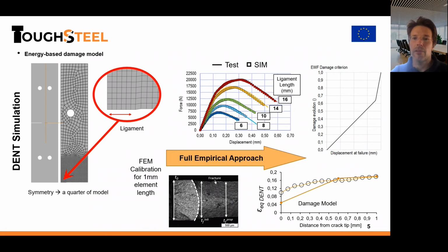To obtain the model parameters, we use a reverse engineering process where we simulate the DENT test and, through an optimization process, we change the model values until we obtain a good fit between the simulation and the results. The simulation model is a quarter of the specimen. We use shell elements, and in the ligament area, we use a 1 millimeter element length. This is also important because the calibration is for the 1 millimeter element length. We have a big element in the crack tip, but in this big element, we have all the behavior of the crack.